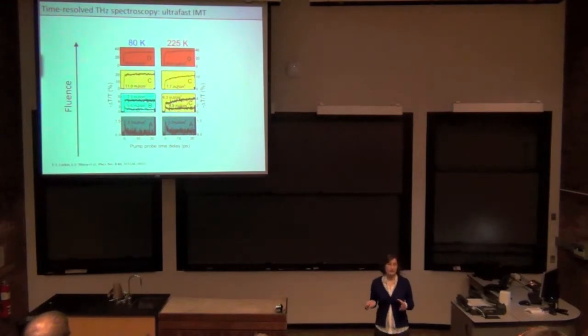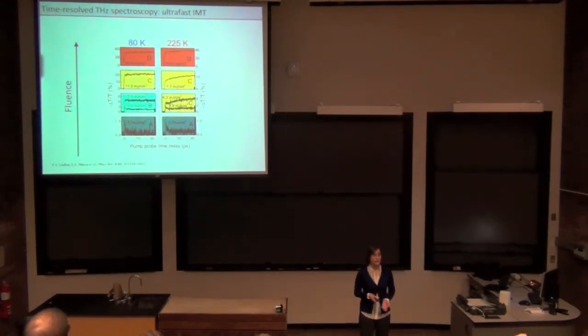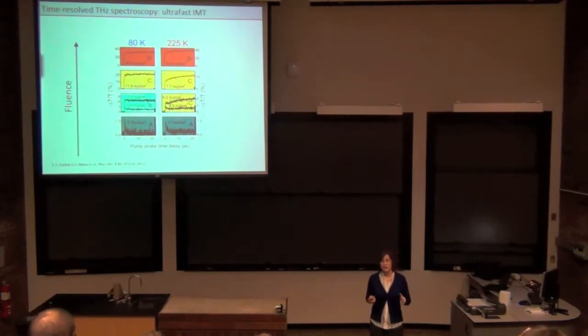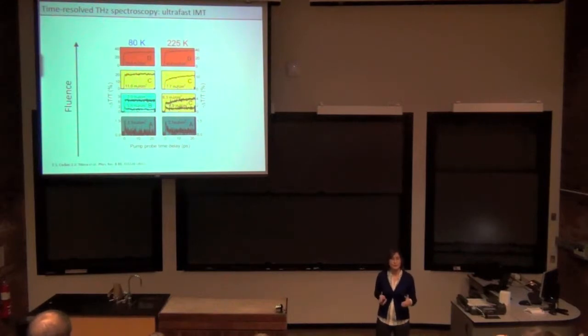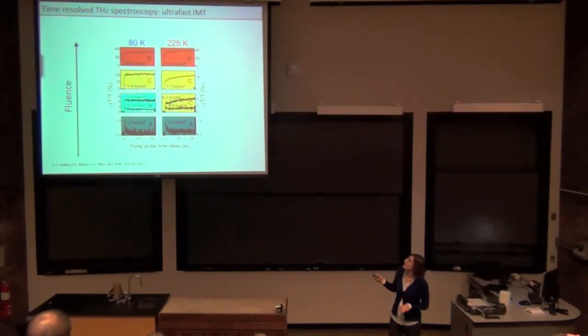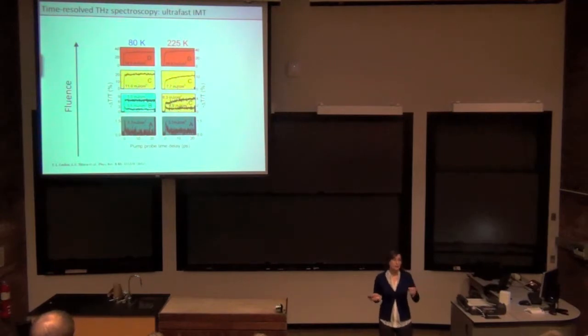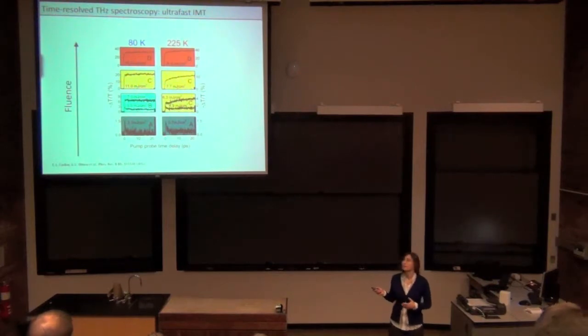So what we did then, now that we know that critical electron density, we've done optical pump, terahertz probe spectroscopy to look at this onset of the photo-induced transition in a wide range of temperatures, going all the way from 10K to the thermal transition, and in a quite wide range of fluences. And this is just an example of some of the decays that we're getting at two different temperatures. So you can see that, depending on where we are in fluence and temperature space, we get different signatures.